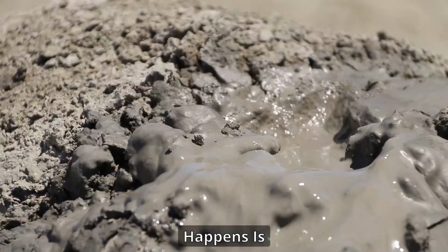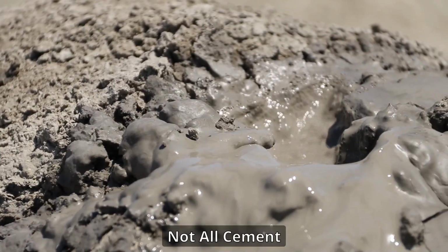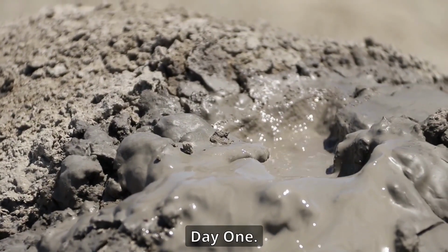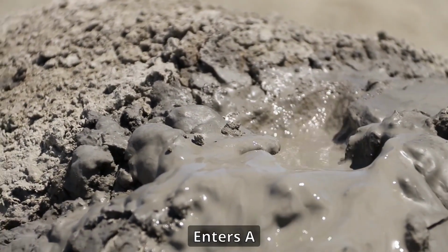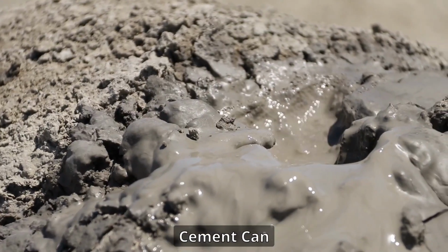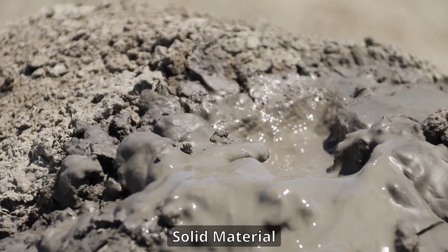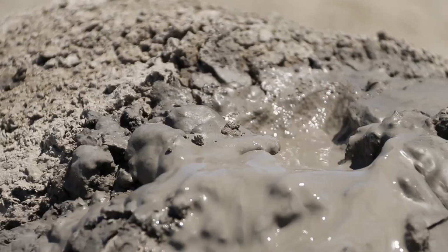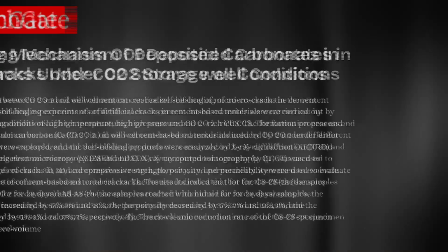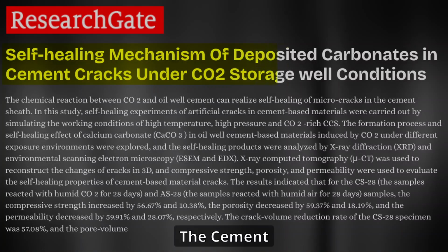One way it happens is continued hydration. Not all cement particles react on day one. If water later enters a microcrack, some unreacted cement can hydrate and create new solid material inside the crack. Another way is carbonation. Dissolved calcium from the cement reacts with carbon dioxide in water and forms calcium carbonate, a stone-like mineral that can fill part of the crack and improve water tightness.